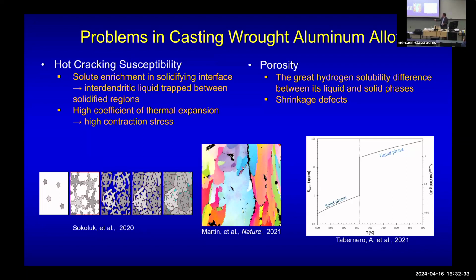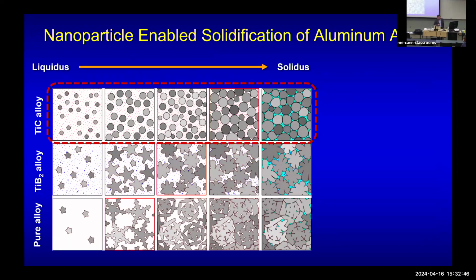So this problem is really the contraction and also the nucleation behavior. And also you have a porosity issue, right? Then they have hydrogen bubbles during the casting of wrought aluminum alloys. And nanoparticles really can solve the problem quite well, right?